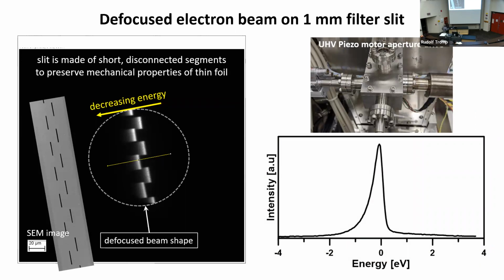Here's this filter slit. Actually, these slits are only a micron wide, and there's a second set where they're only half a micrometer wide, very narrow. We focus the beam and tease it through this little slit. Here, the beam is defocused on this energy selection slit, and so we can draw a trace through here, and we see the energy distribution of the gun. You see it's about, in this case, 0.35 eV wide or so, and has a very long tail, very typical cold field emission electron distribution.